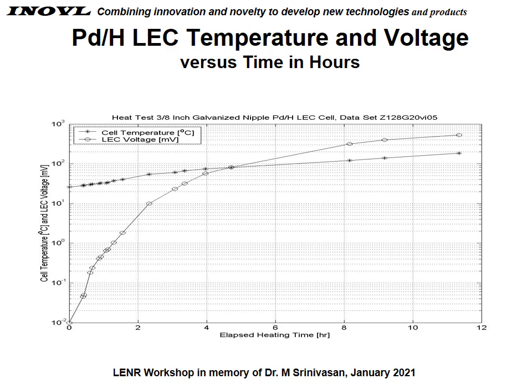This illustrates the data collected on a typical test. You see, we were heating the cell over time, and it took several hours of heating the cell up, and the temperature went from roughly room temperature up to a couple hundred degrees, 180 degrees or so. And over that time period, you can see how the conduction of the cell keeps going up, and it goes up monotonically, but very fast at first.